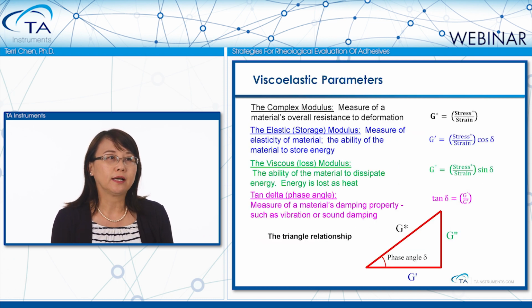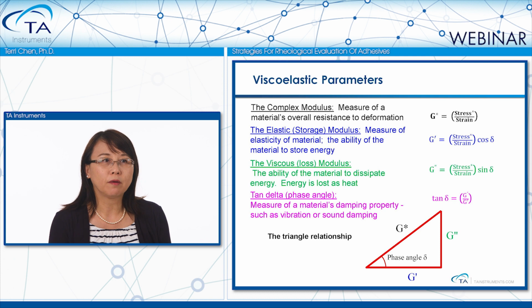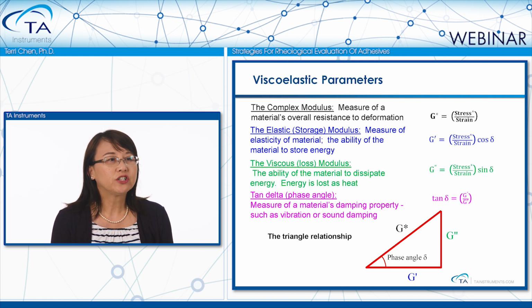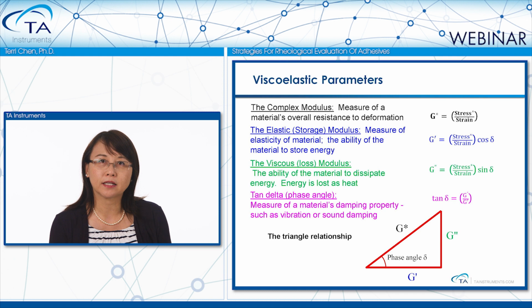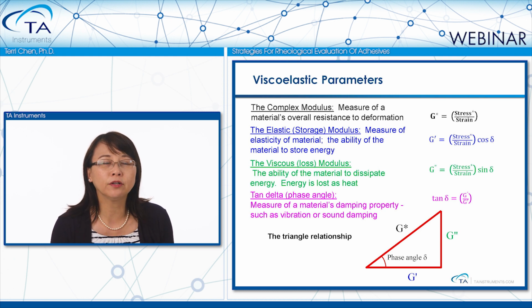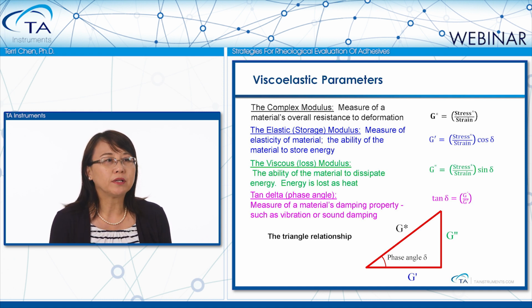In an oscillatory test, the commonly reported parameters are G star, G prime, G double prime, and tangent delta. This slide shows all of the equations for calculating those parameters from rheological testing. G star is the complex modulus. It is calculated from the ratio of complex stress over strain. G star can be separated into two components, which are G prime and G double prime.